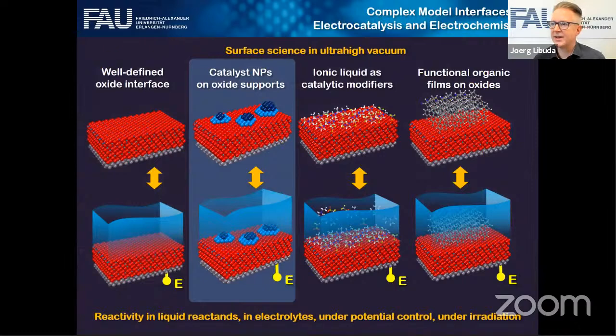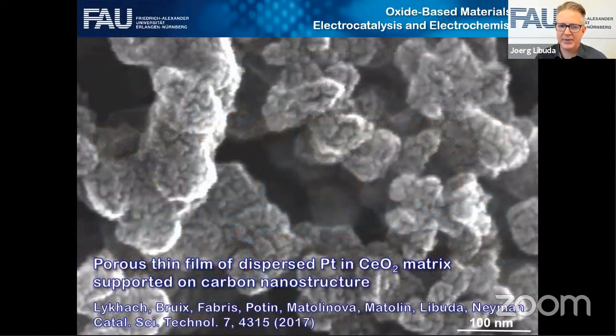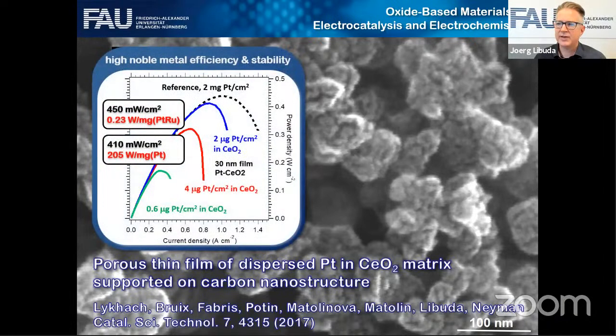So the next step is to look at metal particles. So we put metal particles on such an oxide to look at the electronic and electrocatalytic behavior. Why is that interesting? This is an example of a material that combines such an oxide phase with a noble metal. In this case, it's platinum stabilized by cerium oxide on a carbon support, and you can use this material as anode material in the fuel cell. It shows quite good performance in the fuel cell, and because it contains very little platinum, the platinum efficiency is also very good.